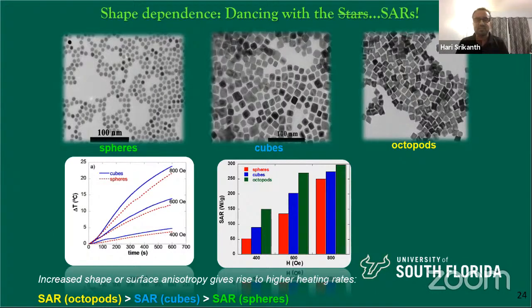There is no question that, under the same conditions, as you increase the anisotropy, as it becomes a lower symmetry system from spheres to octopods, clearly the SAR increases. This is one of our main contributions from my lab, where we told them that, listen, you don't need to look at other materials. Even iron oxide, play with the surface anisotropy, change the shape, and you can enhance the SAR beyond the normal spherical particles that people use.